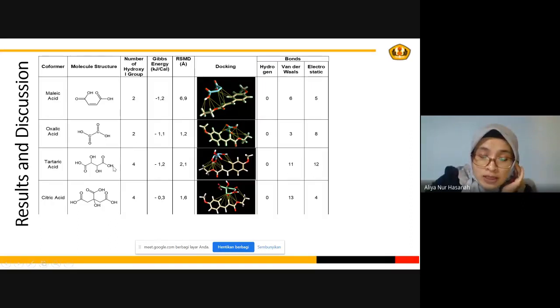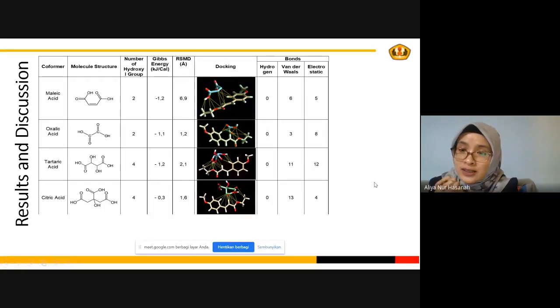Because if we see from the result, the intramolecular hydrogen bond we couldn't see using the software, because when I see the slide, I'm seeing the hydrogen bond between citric acid and APMC, not with the structure itself, not with the citric acid itself. Because with intramolecular hydrogen bonding, the hydroxyl groups in citric acid or tartaric acid bind to itself, right? But when we see the slide, APMC is bound with tartaric acid and citric acid, but the hydrogen bond is like 0.